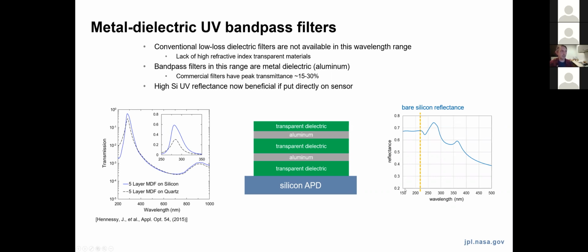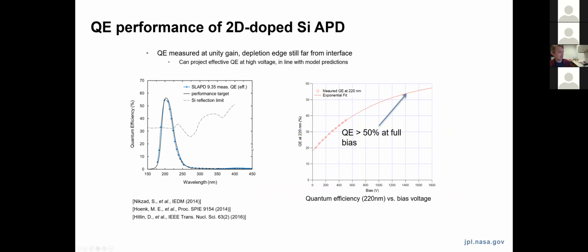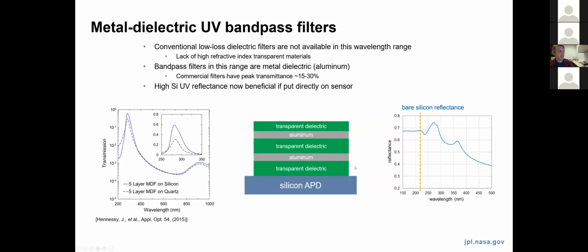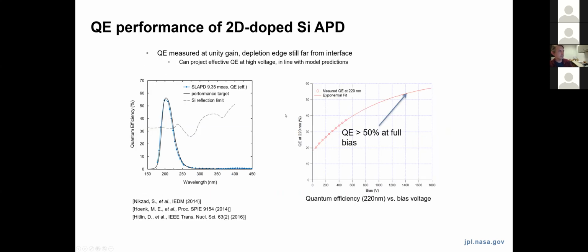And that gets back to what we initially described as a problem, the high reflectance of silicon at short wavelengths is now an effective match to this metal dielectric structure that greatly increases the transmission that you get versus using the same stack on a transparent substrate, for example. Essentially, it's a free cavity in this multi-cavity structure. And so we fabricated avalanche photodiode devices for that physics application, again, with very low response at visible wavelengths, but maintaining this high quantum efficiency in the UV.